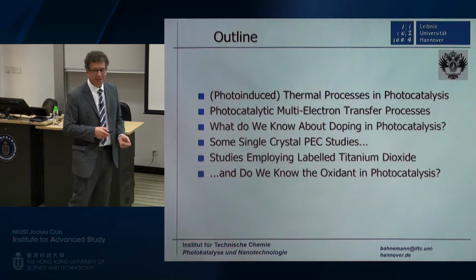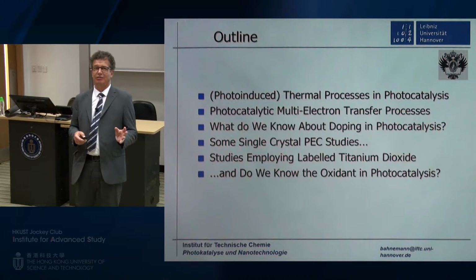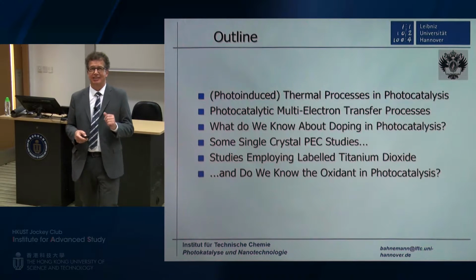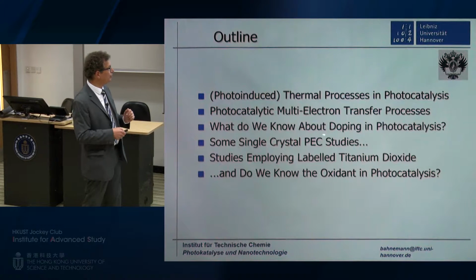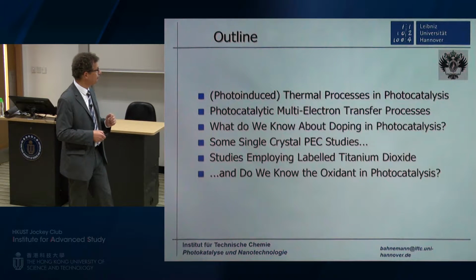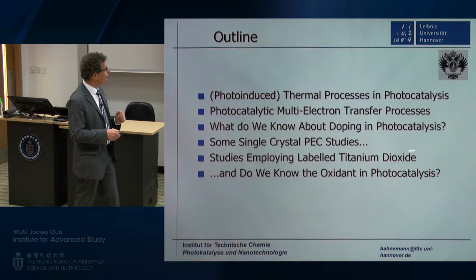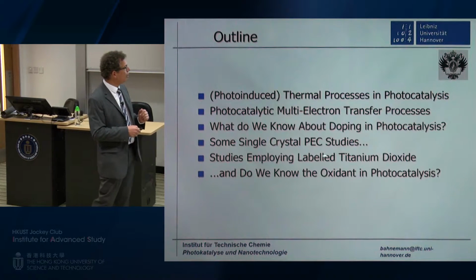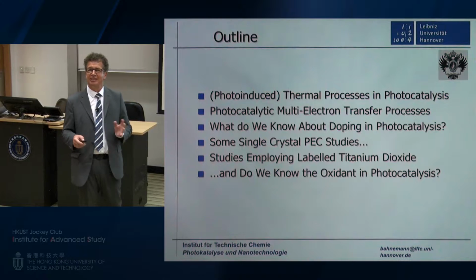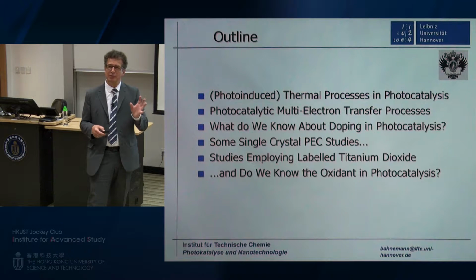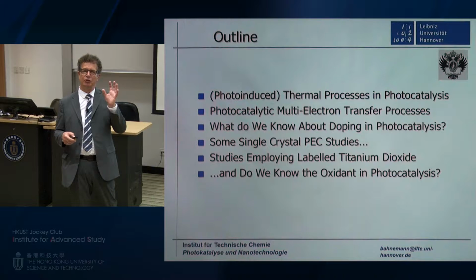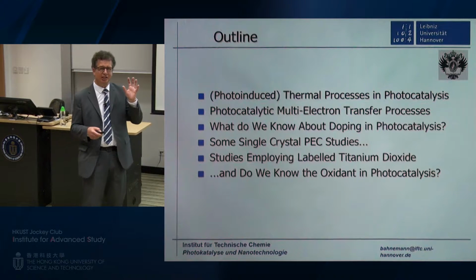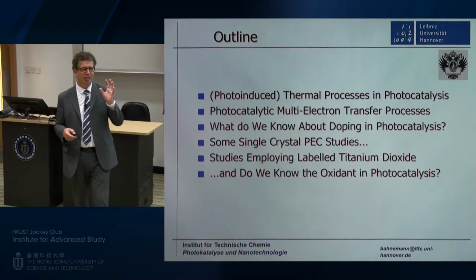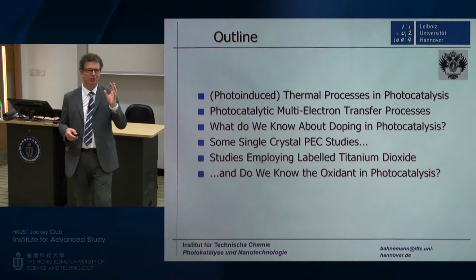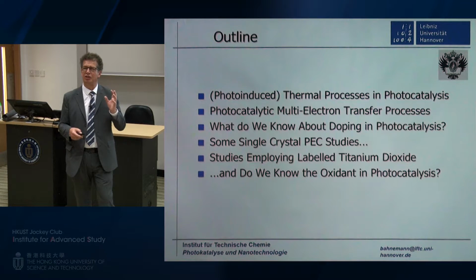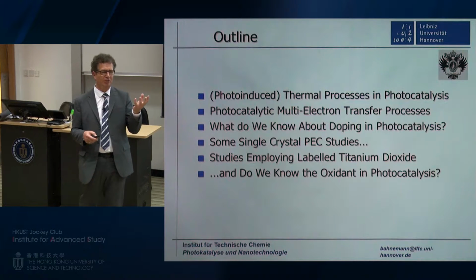Single crystals I find complicated, but I find very helpful, especially if we do photoelectrochemical studies on them. And then we also prepared our own labeled titanium dioxide and looked at its reactions. What we did is, instead of using oxygen 16, we prepared the material with oxygen 18, because we were interested to know where the oxygen comes from if you, for example, form carbon dioxide.